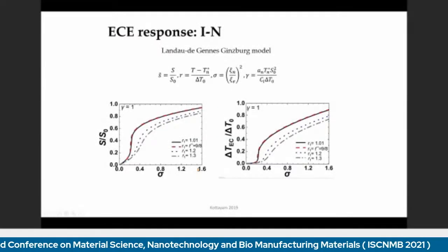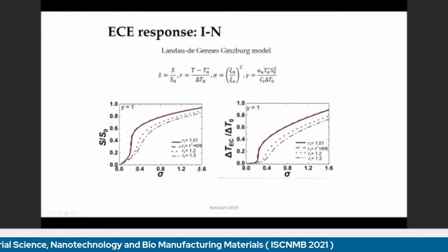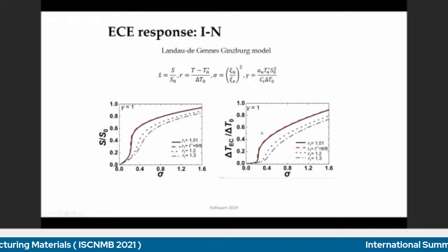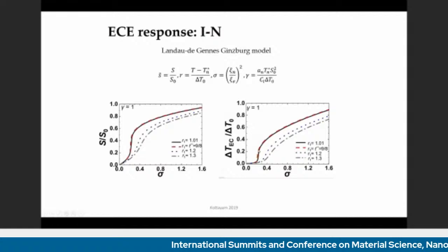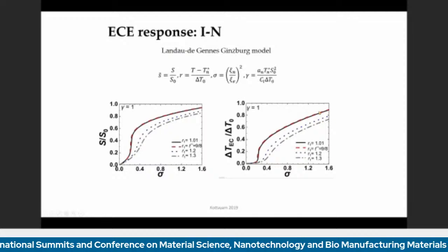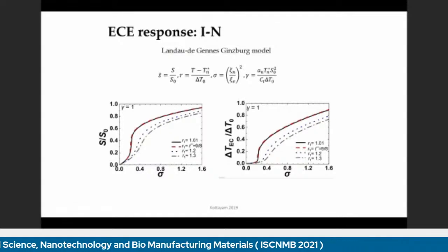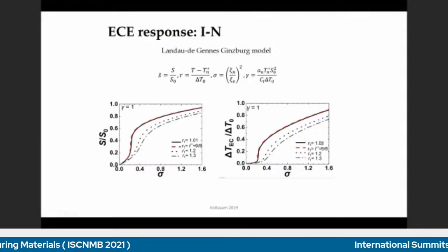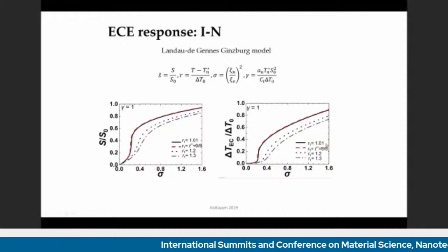And on the right side, we see the calculated change of the temperature due to electrocaloric effects. We also see that the largest response is slightly above the bulk isotropic to nematic transition. We have a larger temperature response in the transition between the isotropic and nematic phase. So it is not just at the transition, it is slightly above this transition because of the electrical field.